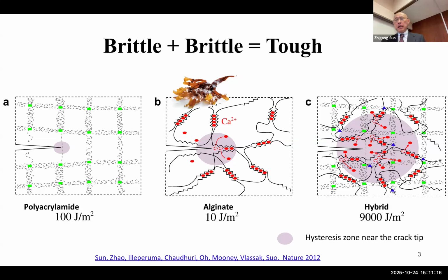So the version of material we made is a combination of the two at the molecular scale. You have this polyacrylamide, and we also interpenetrate it with this alginate. Before you break this polyacrylamide chain, which is a covalent bond, the stress is high enough that it can unzip a large volume of ionic crosslinks. Therefore, you dissipate a lot of energy. The scale of this large volume is on the order of millimeters, much larger than atomic dimension. So this gives us this high number. The toughness is really very high. We call it black magic, dark magic. Brittle plus brittle equals tough.